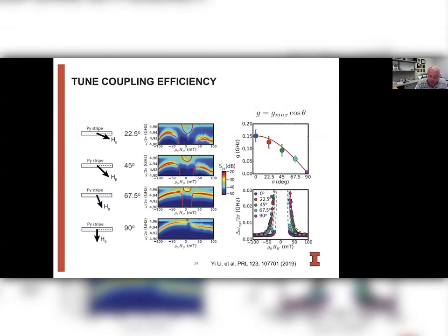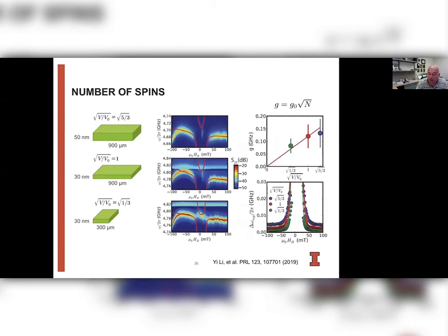Note that there's a little gap here in this data around zero field, because of course, even if we apply the field perpendicular at zero field, the magnetization will still be parallel to the permalloy stripe, and there will be some coupling to the RF field at that point.